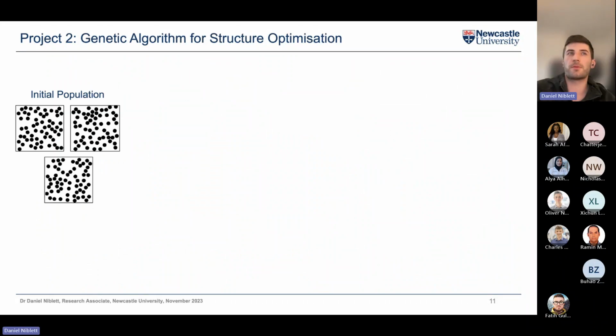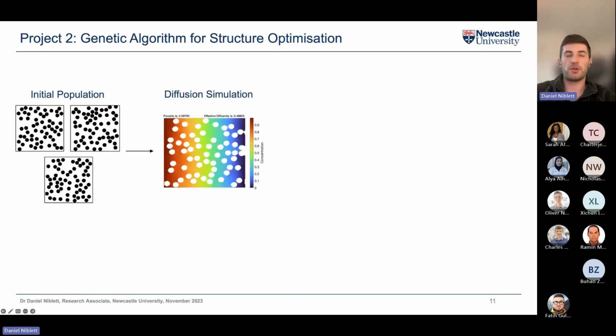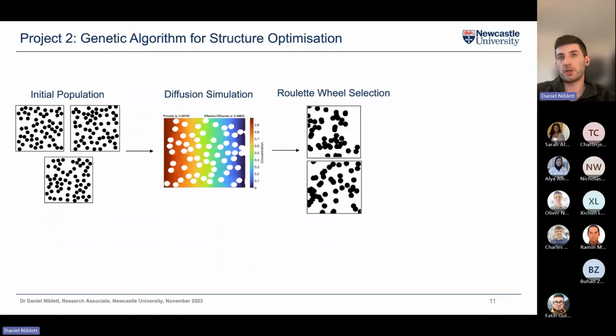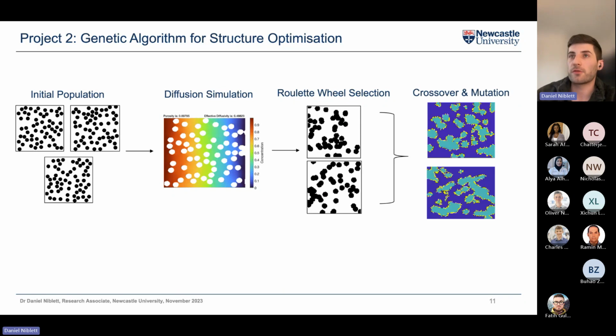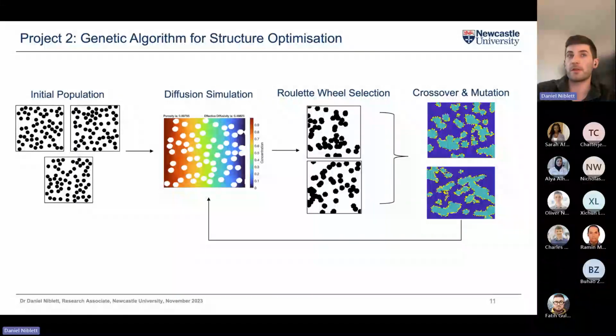And so the genetic algorithm was used for structure optimization, and I had to code this genetic algorithm from scratch because there wasn't a very well working pixel-based genetic algorithm for this type of problem. So you start with an initial population, which is a set of randomized material microstructures. You then compute the diffusion simulation like I showed before, using the model I showed before. I then select the two best parents using a roulette wheel selection. So the best performing structures get selected. And then through some customized crossover mutation algorithms, you essentially merge together or cross over the two parents to create a set of children microstructures, which you again loop back around to the simulation and keep repeating this until some type of optimal microstructure evolves from this algorithm.